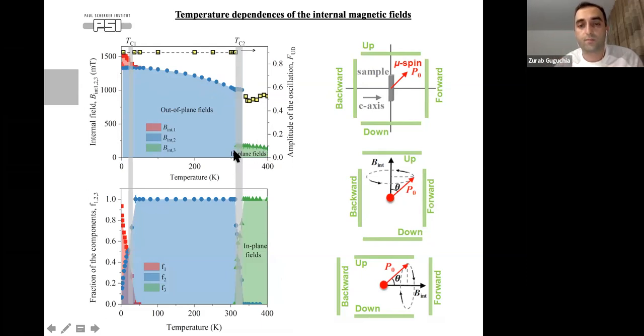So we see here in-plane fields, and then below 300 Kelvin, the internal field is pointing along the z-axis. For this, we had to do experiments to look at the anisotropic behavior. We have four different positron detectors, and depending on which direction the internal field is in the sample, if the internal field is along the z-axis, then we see a large amplitude in up-down, and there should be no signal coming from forward-backward. So with this kind of measurement on a single crystal, we can see the direction of the internal field. And this is what we used here.